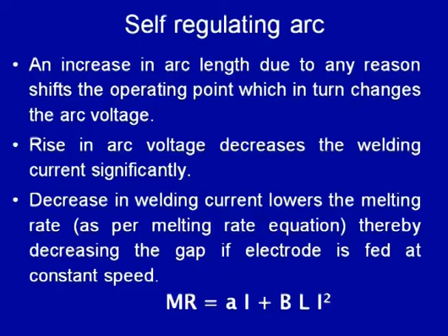So, any change in the arc length will change the welding current, which in turn will change the melting rate, and the change in melting rate for a constant feed drive system helps in maintaining the arc length. For example, an increase in arc length due to any reason shifts the operating point, which in turn changes the arc voltage. So, whenever there is an increase in arc length, arc voltage increases, and with constant voltage type power sources, an increase in arc voltage is always associated with a decrease in welding current, and so the reduction in welding current in turn decreases the melting rate.